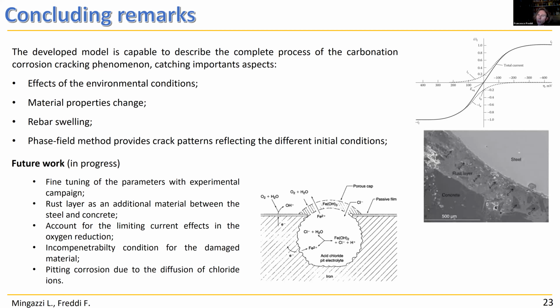Whereas the corrosion due to CO2 is evident, the pitting corrosion may be hidden within the concrete element, because it does not lead to the expansion of the bar, but only a reduction of the area of the reinforcement that may lead to a sudden collapse of the structure. So I've concluded, and thank you very much for your attention.